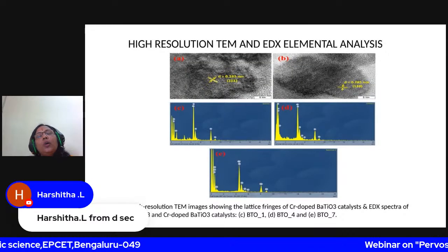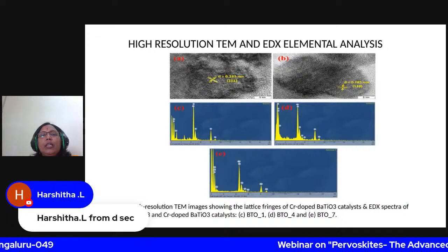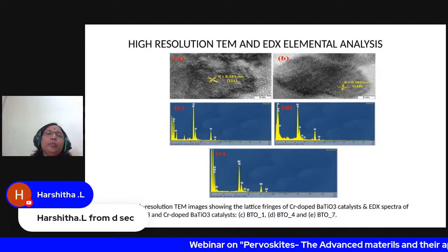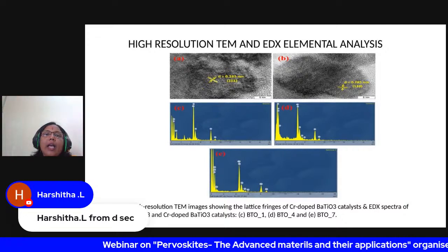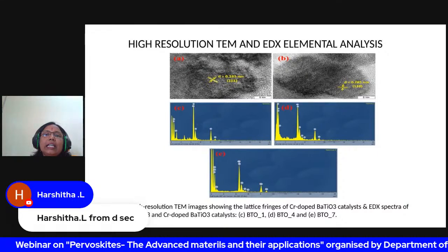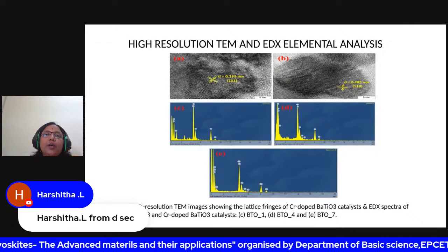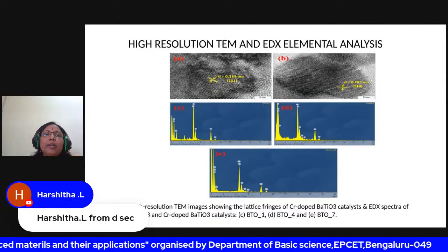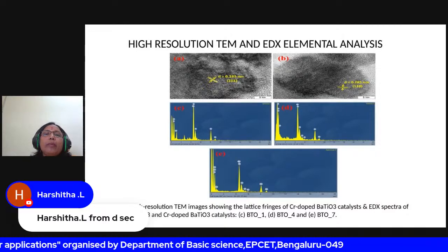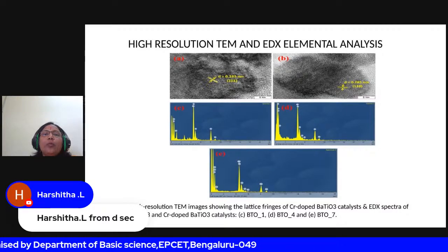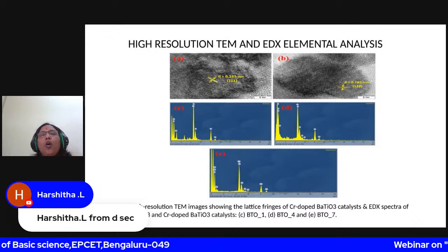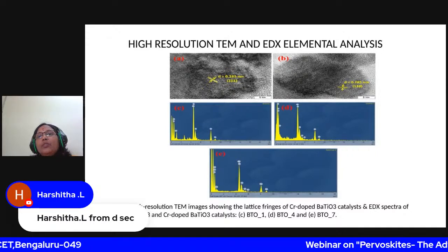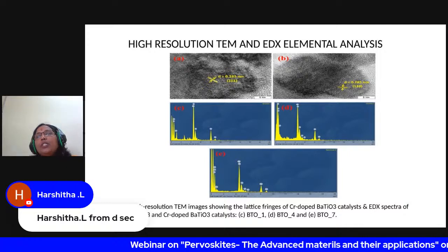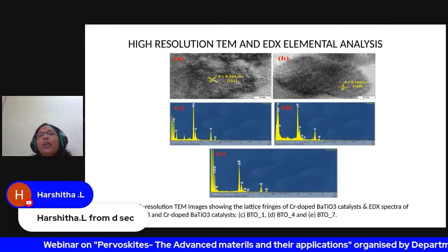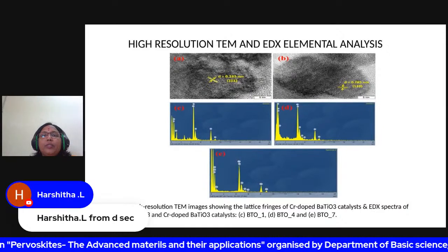So we also measured the high resolution images of 2.5% chromium doped. This thing you can see, this is the high resolution TEM image. You can see the clear lattice fringes, and we have calculated the d spacing between these two crystal planes, and it comes to 0.283 nanometer, which is the 101 plane of the CO synthesized material. And this one here, we calculated 0.28 nanometers, which belongs to the 110 plane of 2.5% chromium doped in microwave synthesized materials.